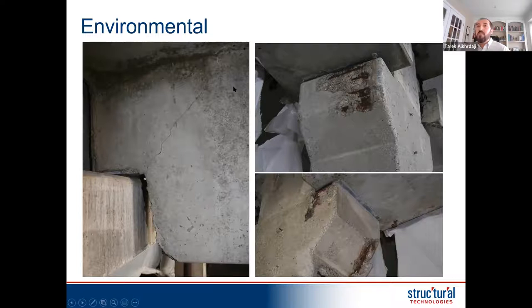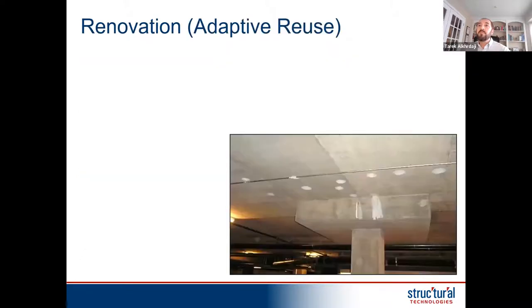Friction reduces the shear capacity and you end up with some cracks. And in many cases we've seen collapse of structures, or partial collapse, because some of these forces are so high that they can cause failure. The photo to the bottom right, maybe you cannot see it very well, but there's a crack almost at the edge of the corbel, which combined with corrosion and high movements, there's a very high potential for failure. And in this project, there was one failure of one of the corbels.